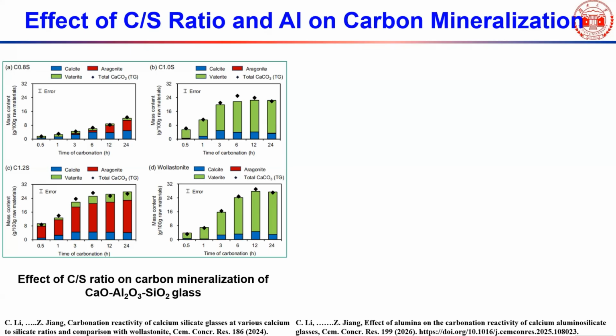On the other hand, if you compare, this is the calcium to silica ratio 1 glass, and the bottom figure is actual wollastonite, a crystallized calcium to silica ratio 1 calcium silicate. You can see the carbon dioxide uptake becomes higher.